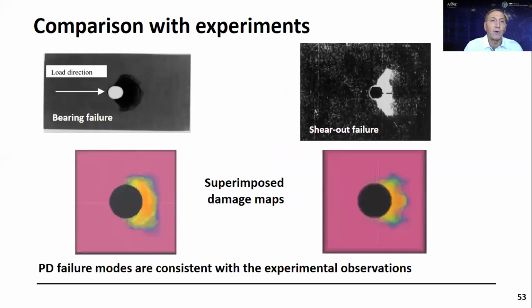Now, this is a slide that I want to show you. So I superimposed all of these plies. And as you can see here, the damage maps very nicely capture the bearing failure and the shear failure. So it's very consistent with the experimental observations.